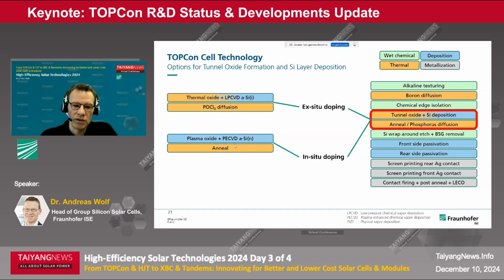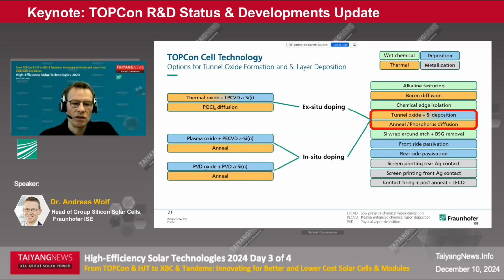For example, in a PECVD reactor, where you first use a plasma oxidation to form the interface oxide and then can deposit a phosphorus doped layer by PECVD, which is then crystallized in a subsequent annealing step. And the same can be done by a PVD approach with a PVD oxide and a sputtering of the doped silicon layer. And recent progress here is also that you don't use any single layers anymore, but multi-layers that are deposited with intermediate oxide layers to decouple surface properties of contact and interface oxide.